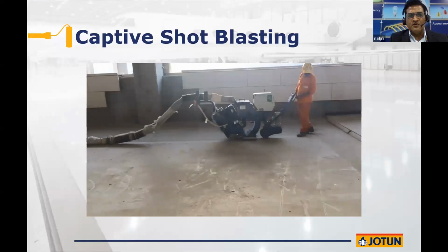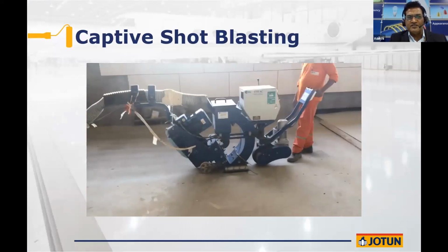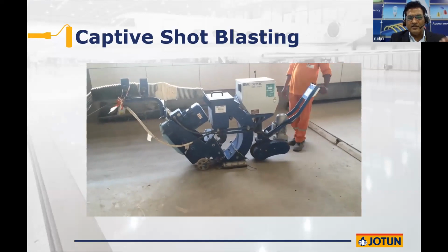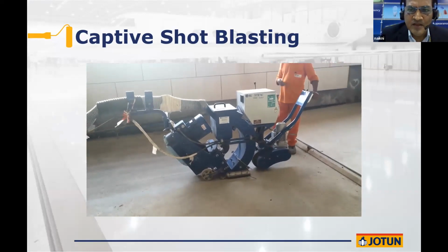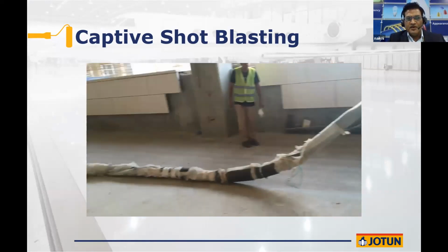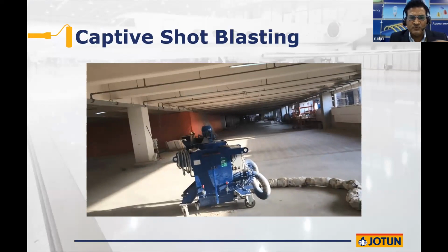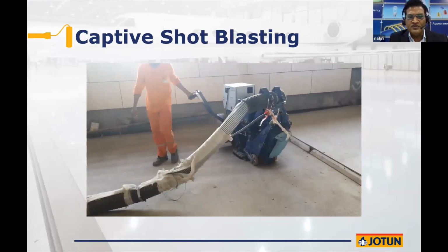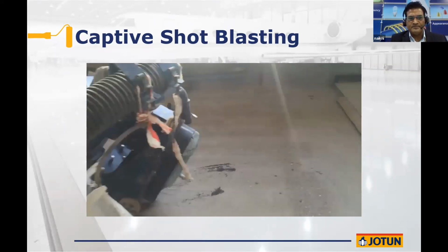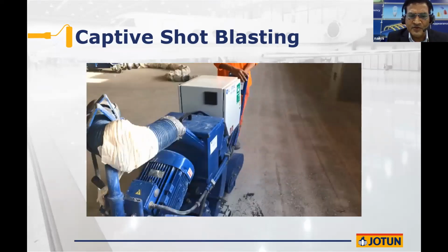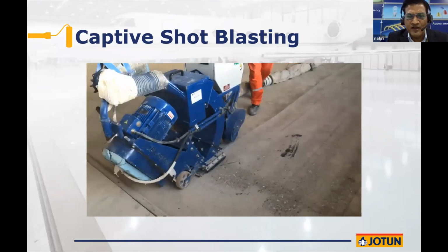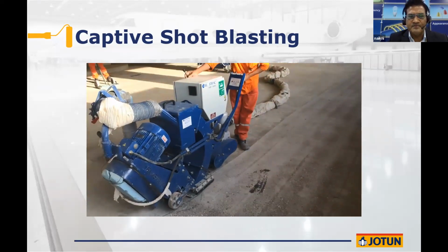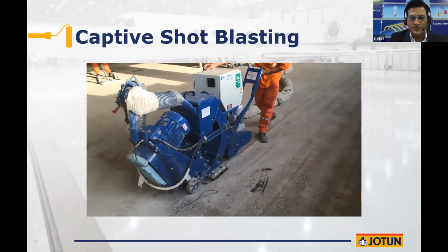There are different ways. The most preferred method is the captive shot blasting method, where steel shots are fired at high intensity onto the substrate, thereby eroding at least a millimeter on average of the top substrate, and at the same time creating a profile so that the coating system can anchor itself on the substrate. Now you can see very clearly as we go closer, there's a clear profile being created on the concrete substrate. This is called the captive shot blast machine system, captive shot blasting method.